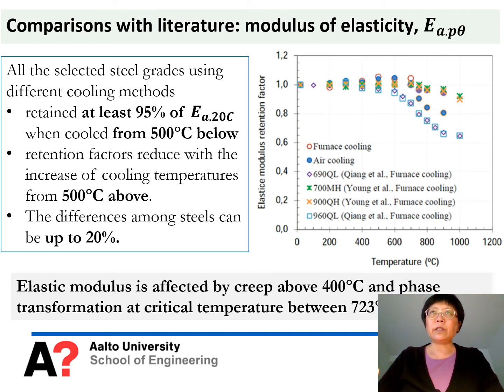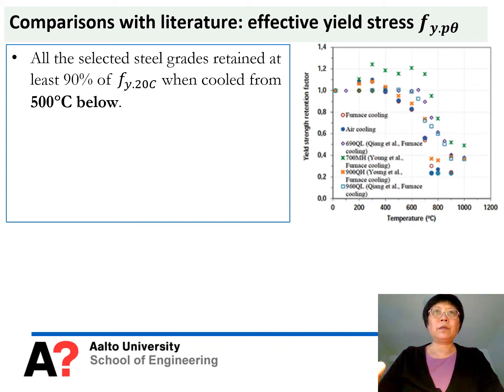The reason is basically that the elastic modulus is affected by creep above 400 degrees, and also by the phase transformation at the critical temperature between 723 and 910. And this slide shows the comparison result on effective yield strength.